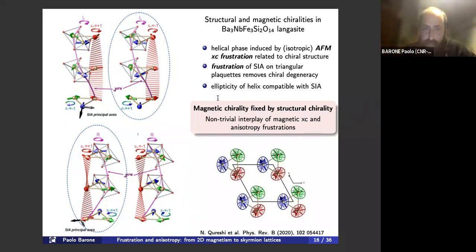And I will not enter into too many details here, but basically this has been proven experimentally that there are helical chains in this structure whose chirality is fixed to the structural chirality through the frustration of the single ion anisotropy in this triangular plaquette, which forms the chains. And also in this case, in principle, one would also have the Dzyaloshinskii-Moriya interaction, but the Dzyaloshinskii-Moriya interaction could not explain the presence of an elliptic deformation of the helical modulation along the chain, which is instead naturally explained in terms of this frustrated single ion anisotropy.